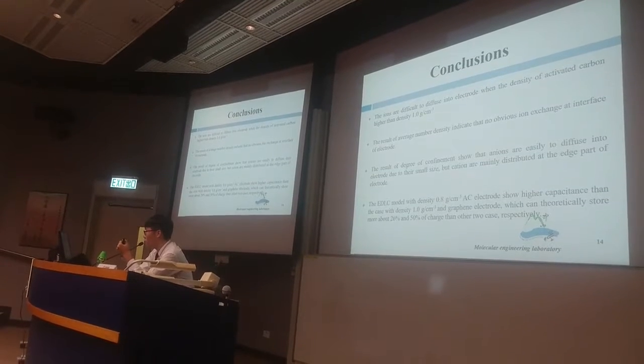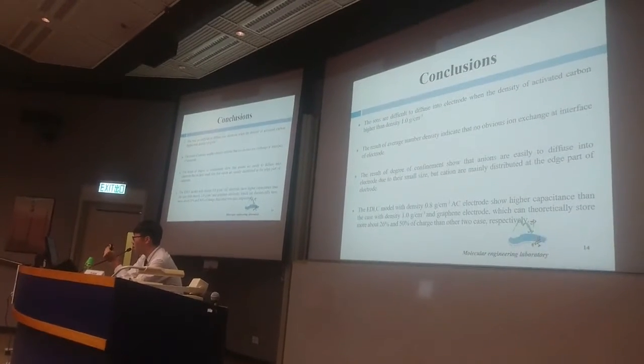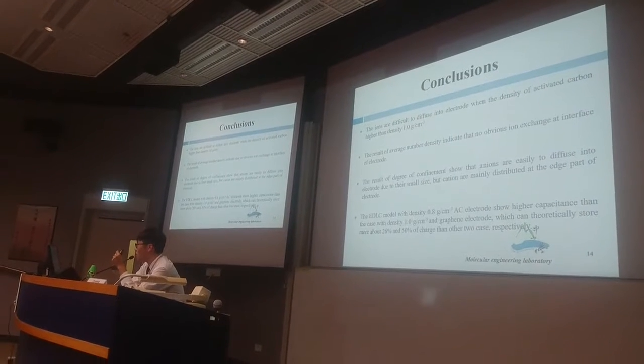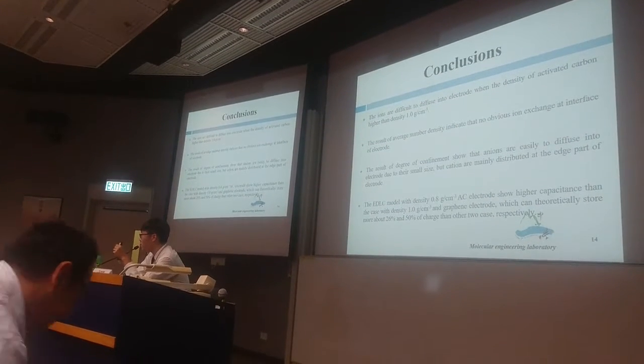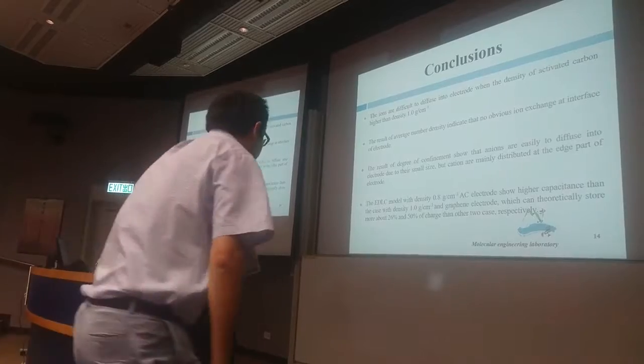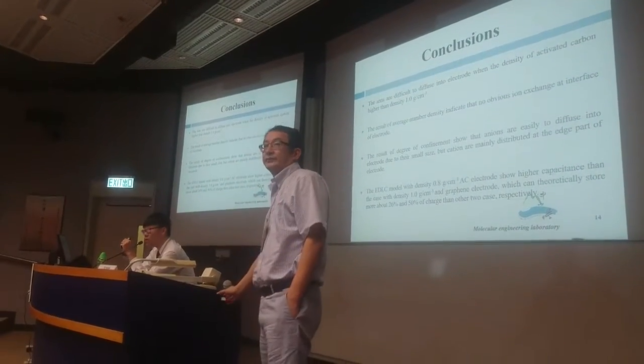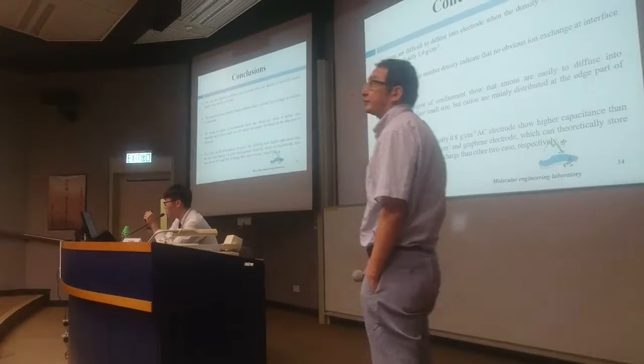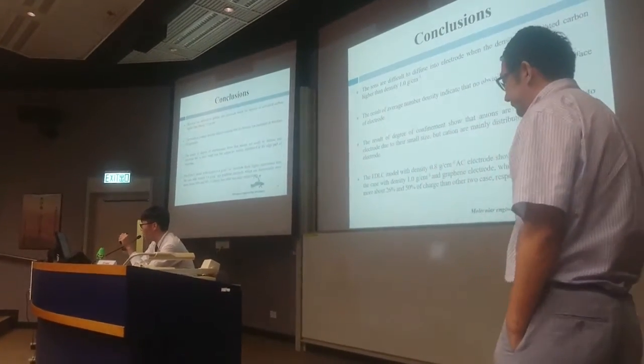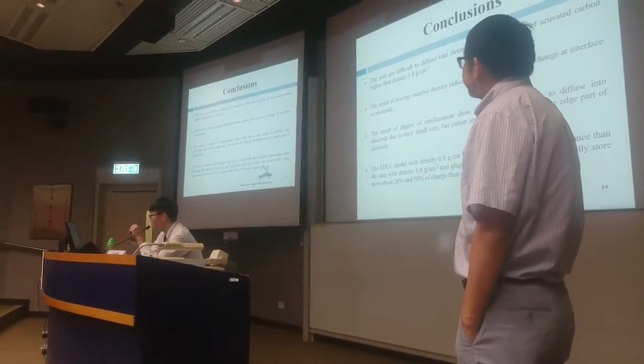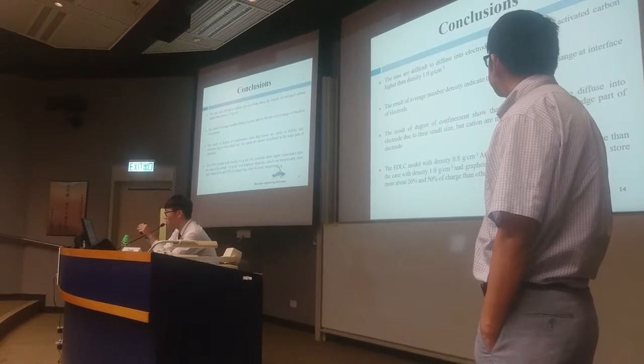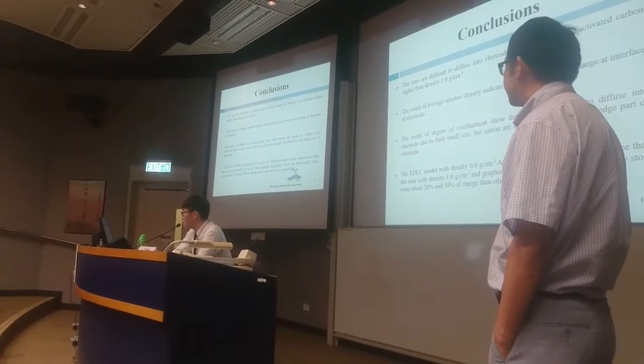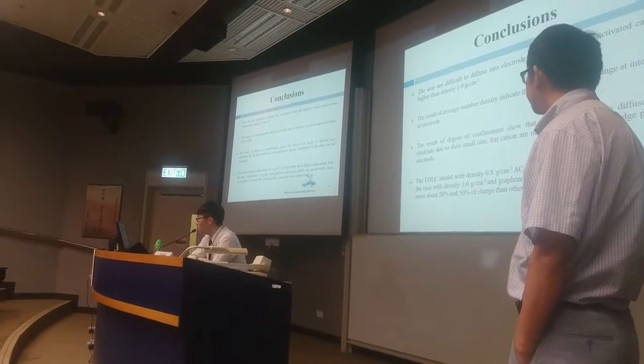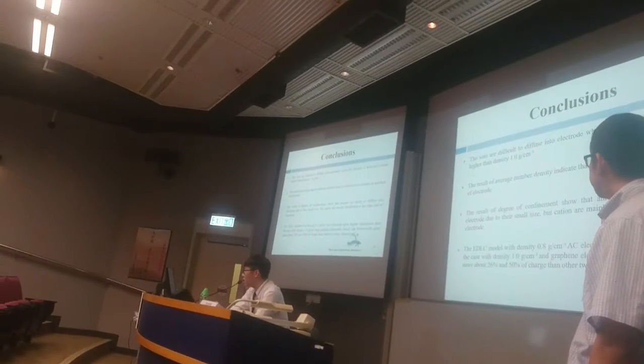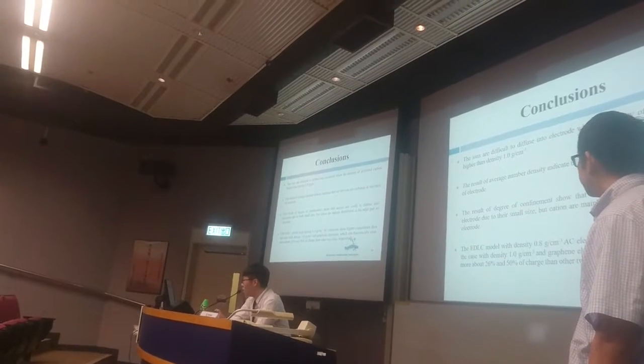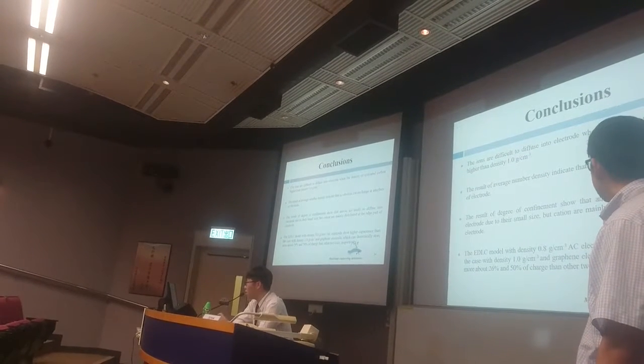Finally, we make some conclusions from my work. The ions are difficult to diffuse into the electrode when the density of AC electrodes is higher than 1.0. The result of average number density indicates that there is no obvious ion exchange at the interface of electrodes. The results of the degree of confinement show that anions easily diffuse into electrodes due to their small size, but cations are mainly distributed at the edge part of electrodes.